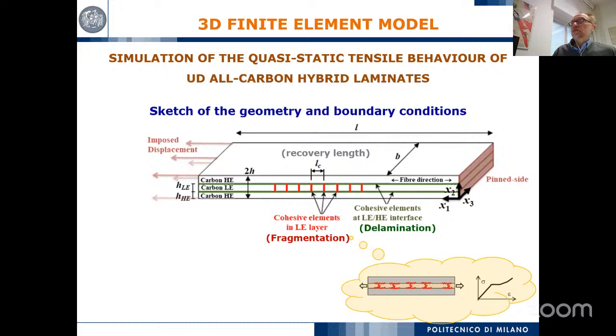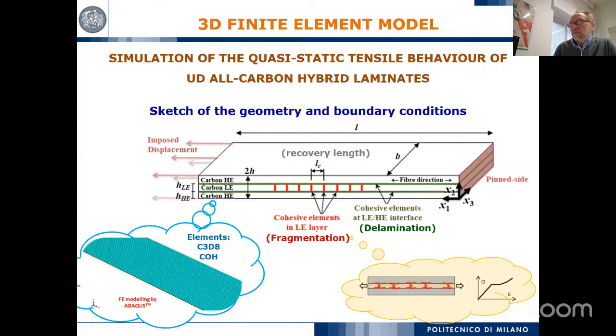Mainly what we simulate is the fragmentation in the low elongation ply, and this has been simulated by introducing transverse cohesive elements in different positions at a certain distance that was lower than the recovery distance for this material. We also want to simulate the delamination, so we use cohesive elements at the interface between the low and high elongation plies. What we want to simulate is exactly this damage mode evolution that creates the pseudo-ductility behavior. This was performed using a finite element model in a commercial finite element code.